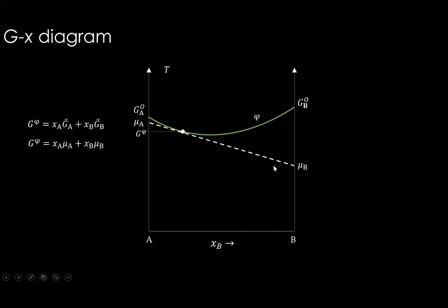So what does this line represent? The entire curve is above this line. So this is the minimum possible Gibbs energy, when A and B have this chemical potential and their combination is giving us this Gibbs energy. For this overall composition, this is the lowest possible Gibbs energy, and that is the equilibrium state. So the entire curve is above this line. That is the minimized Gibbs energy. Fine.